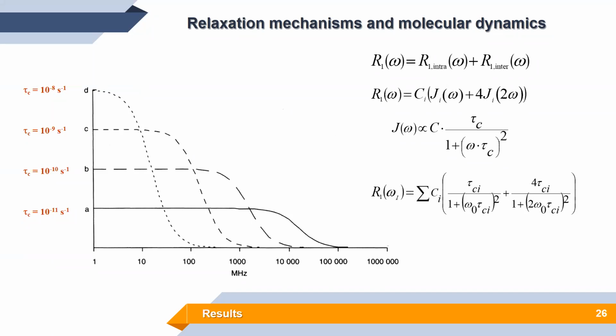The former results from the fluctuations of the interproton distance between separate molecules. The latter comes from the fluctuations of the orientation of the spin-spin axis in the molecule, resulting from the rotational diffusion. Under the assumption that both types of molecular dynamics are stochastically uncorrelated, those intermolecular and intramolecular dipole-dipole interactions contribute additively to the experimentally observed T1 relaxation time.